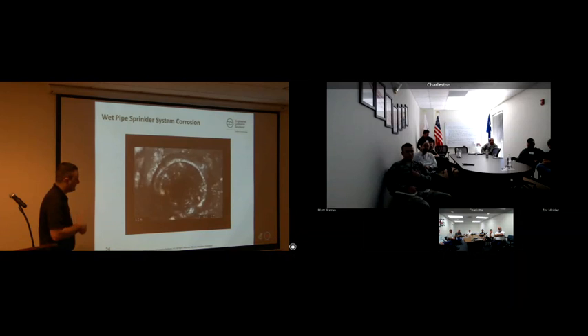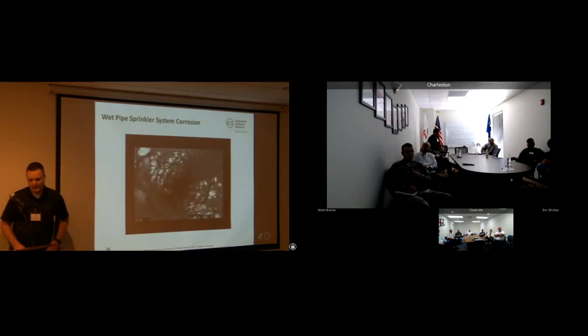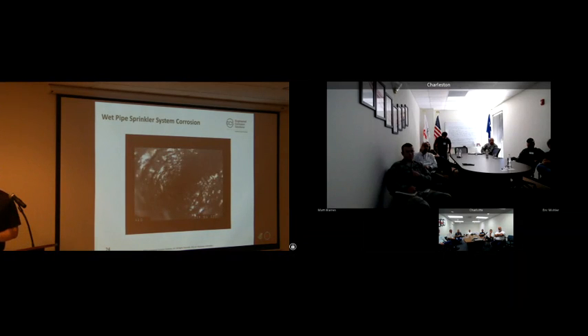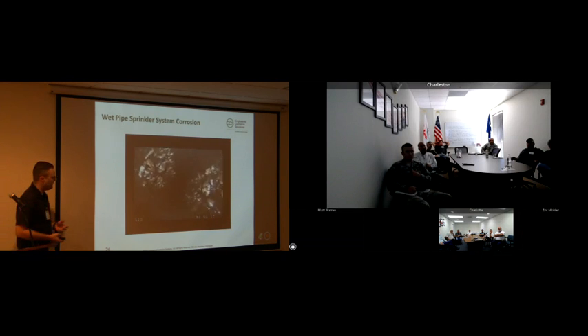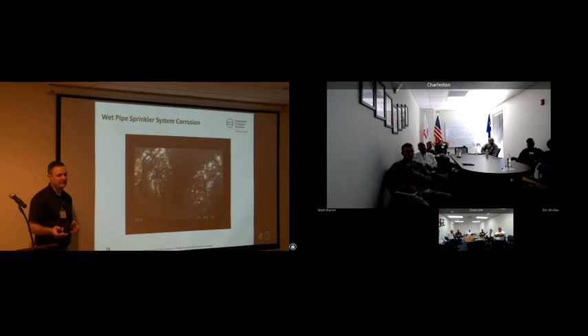Here's a video. This is a wet system. This was in an unconditioned manufacturing warehouse. But you can see once again, where the air was, there was virtually no corrosion. But you can see every one of these bumps, we call them tubercles, every one of those bumps, underneath them, there's a pit. There's a pit forming, there's a potential leak happening. So you can see that corrosion does absolutely, and you can see how rough that pipe wall was. That affects your hydraulics as well.